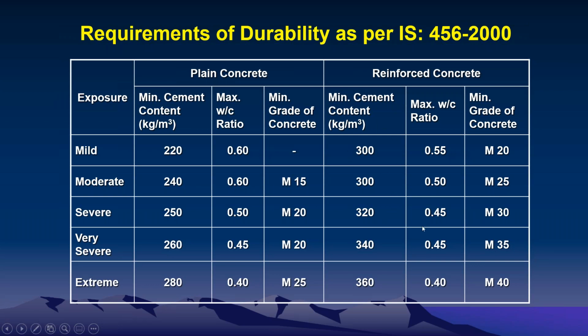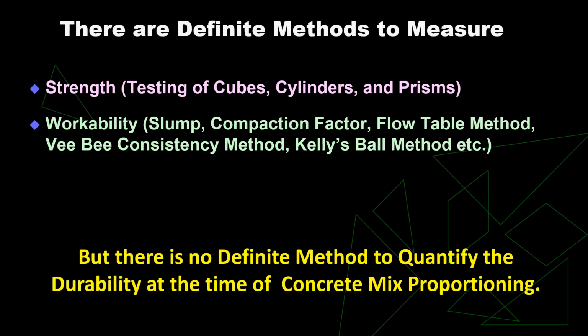These are called prescriptive parameters. Prescriptive means, suppose you are designing concrete for severe exposure, your minimum cement content has to be 320, your maximum water cement ratio has to be 0.45, or a minimum grade of concrete. See, you are prescribing a concrete with them, but you are not sure whether it is going to give your required durability or not. I'll explain in detail. As I explained earlier, there are definite methods to quantify strength and workability, but there is no definite method to quantify durability.